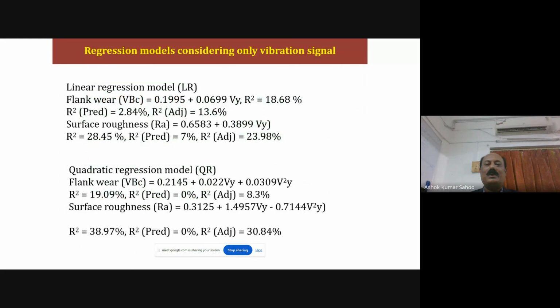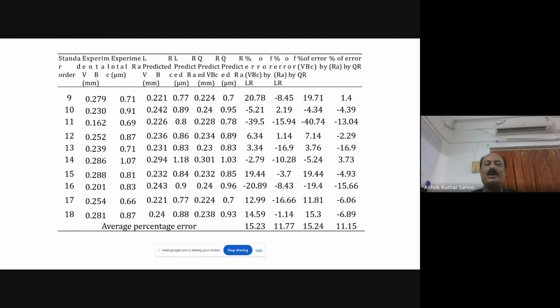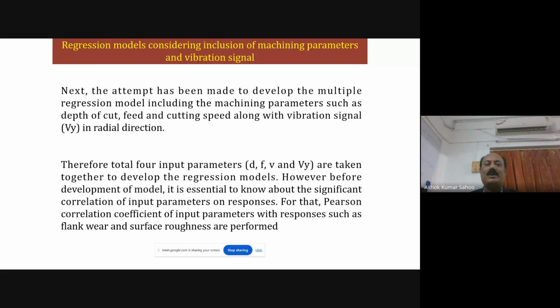We developed models, first a linear regression model and also a quadratic regression model. First, we observed the linear regression model considering only the vibration signal, which was found to be insignificant because the R square value is very low and the errors are very large. Then we developed another regression model considering the machining parameters and vibration signals, all four taken together. However, before developing the regression model, it is essential to know the significance of the correlation of the input parameters like depth of cut, feed, speed, and vibration with the output.